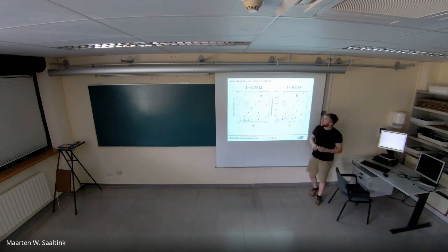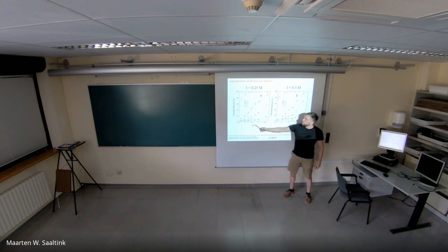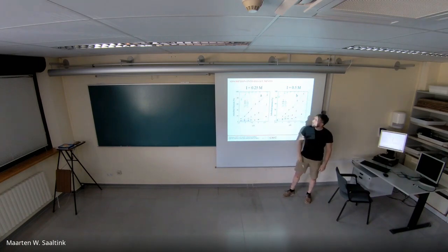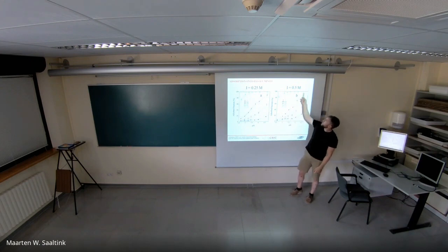So the results of the adsorption here in basaluminite, this is solution 1 and solution 2. We don't see much difference from one another. We see in both that the adsorbed fraction increases as the pH increases, and we see that heavy rare earth elements, which is for example terbium, are more adsorbed than light rare earth elements, which is for example lanthanum, and middle rare earth elements, of course, are in the middle.